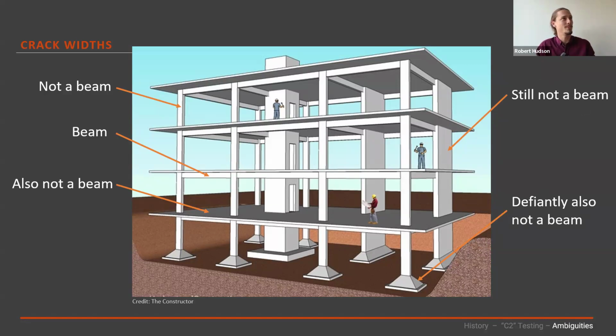This 0.8 mm crack width apparently has been developed for reinforced concrete beams. It's not immediately obvious to me that that translates perfectly well to other elements in a reinforced concrete structure. Maybe it does. Not sure. From a design point of view, the really important thing to keep in mind is that if you're using a C2 capacity, what you actually are allowing for is a crack width up to 0.8 mm. If for whatever reason you're expecting cracks larger than that, the C2 capacity is probably not very appropriate. It's probably actually overrating the capacity. Similarly, if you're expecting cracks less than that, then your capacity is going to be quite conservative.